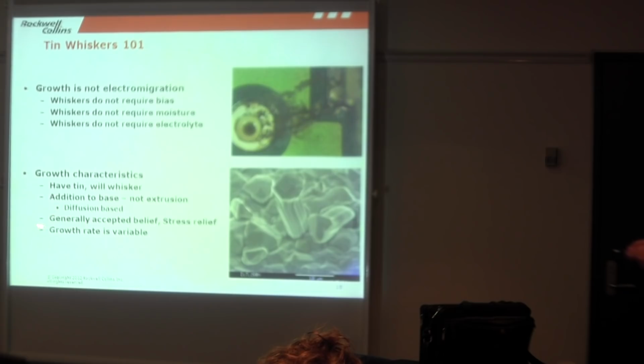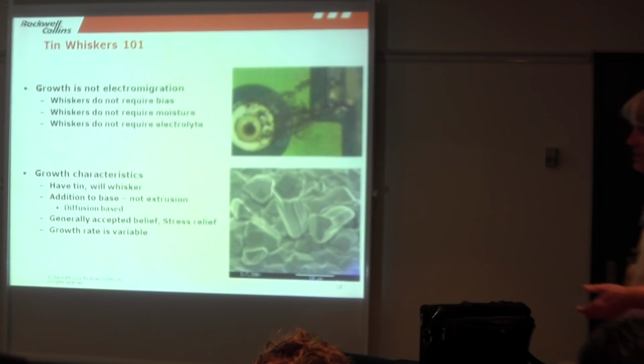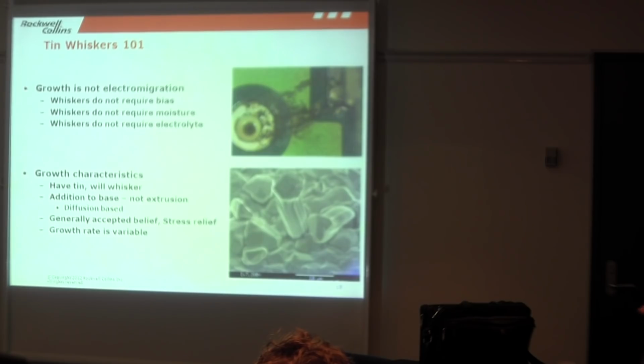It is industry consensus that it is stress in the plating. And the reason the tin grows a whisker is to relieve stress. And other metal systems do that. Tin, lead, gold, a lot of them do. Unfortunately, because tin recrystallizes at room temperature, it's primed to say, okay, I'm going to get rid of stress right now. And what's it do? Okay, I'll grow a whisker.